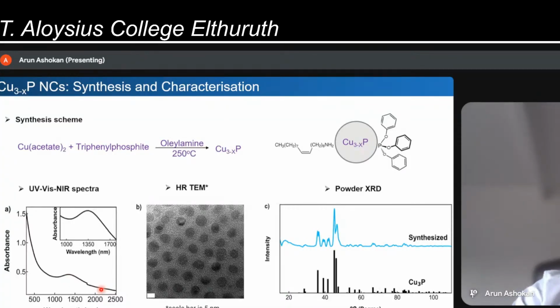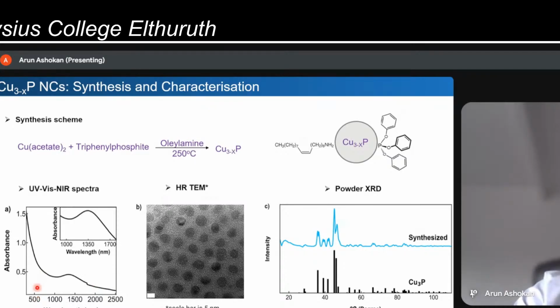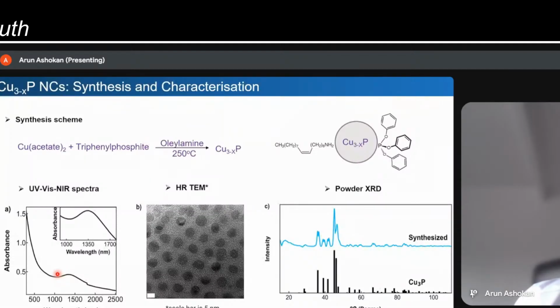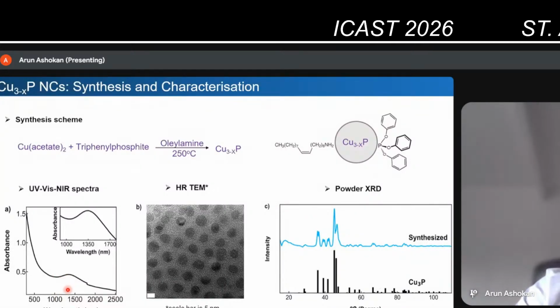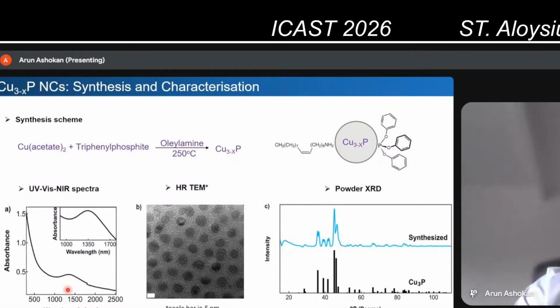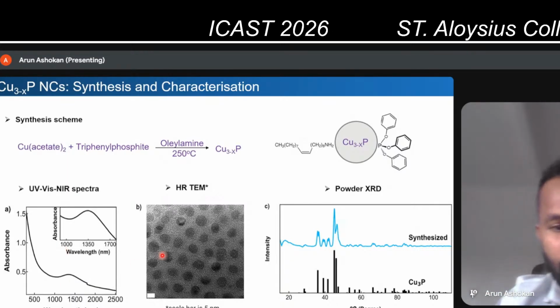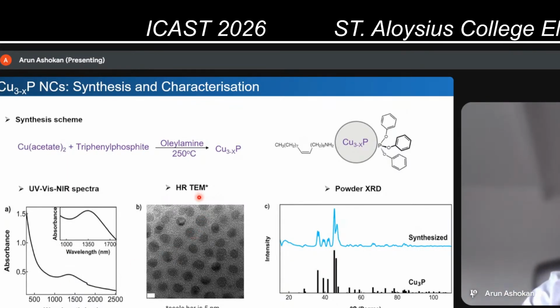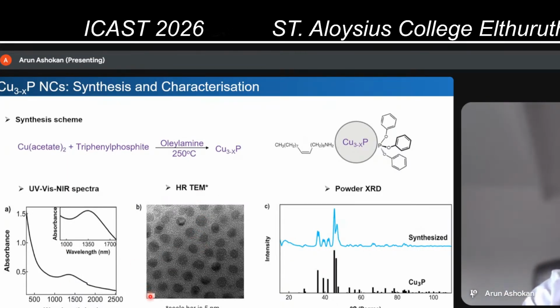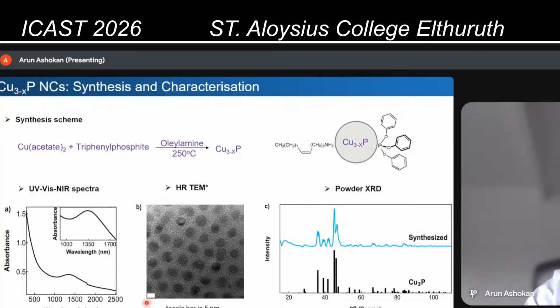In gold, this absorption comes around 500 nanometer, if you guys remember. But here, as I said, because the free carrier density is between 10 raised to 16 to 10 raised to 21, in that range, you'll get the plasmon resonance in the near infrared region. And if you take the transmission electron microscopy images of these nanocrystals, they are quite small, roughly 5 nanometer. The scale bar is 5 nanometer.